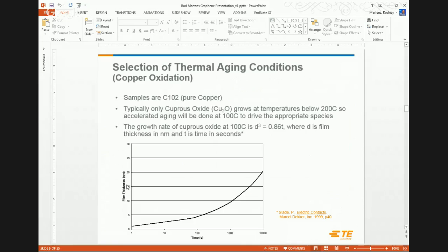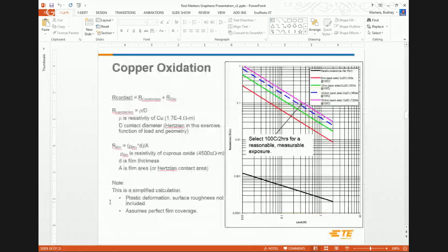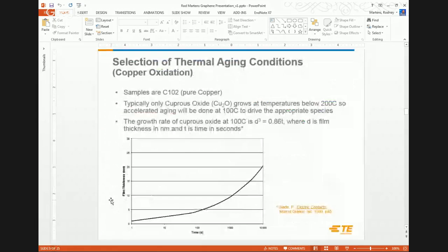To understand how the oxide grows, we want to make sure that we're growing the right type of oxide. So this would be cuprous oxide that would happen at temperatures below 200 C, or somewhat relative to room temperature. And then we want to age it so that we generate that specific type of species. And from this curve here, we can see the relationship between time and temperature and the film thickness.